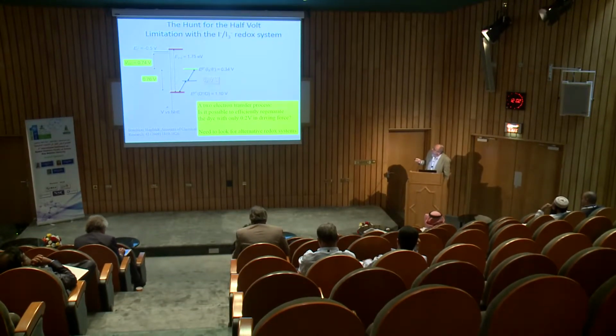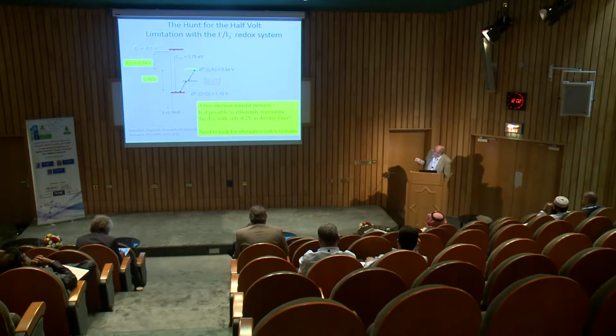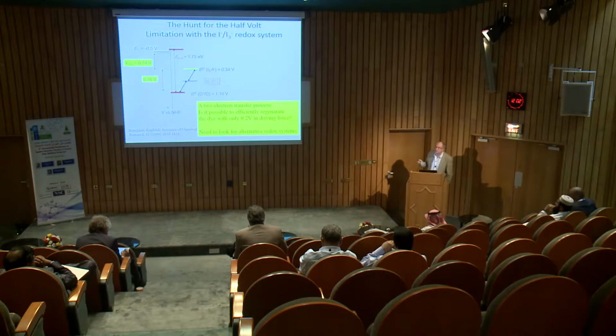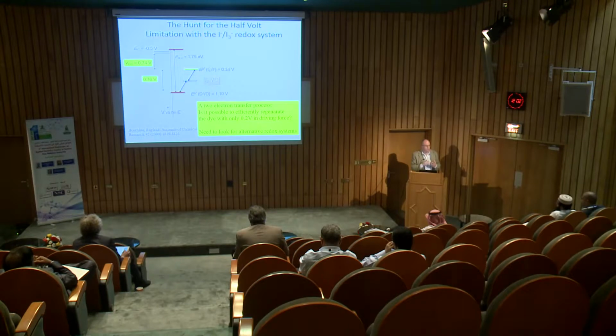And our conclusion after some studies was that the mechanism for the regeneration is that the iodide brings the electron back to the dye, you form an iodine radical, and that redox potential is the crucial one for the driving force to regenerate the dye here. And that is about 0.3, 0.4 volts higher than the dye state. And that was our conclusion, saying that the driving force in the system to regenerate the dye is actually not 0.7, it's 0.3, 0.4, and perhaps we can't do so much more with the iodide system. The rest we need to use to create the I3 minus system.